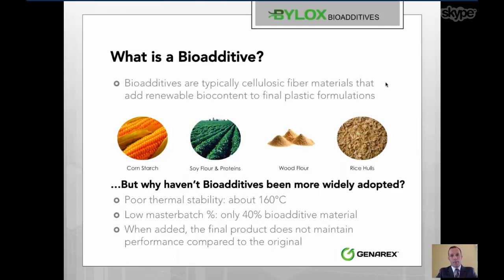What is it? To those that don't know, what is the space that we play in? We are an additive and or a filler. Typically, these products are cellulosic fibers. They have that long aspect ratio that adds stiffness and reduce impact of products. The problem that other people have run into in the past is that with this long aspect ratio, the product doesn't maintain the same performance as its precursor. So if you use it as a resin extender like Bylox is intended to be used, it tends to embrittle a finished product. Also, bioadditives historically are not very thermally stable and generally can't be dispersed easily into different products.